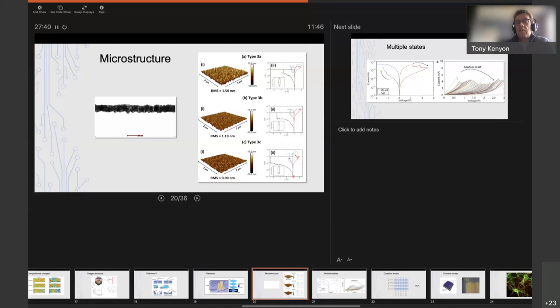What I didn't tell you at the beginning was that we start off with an oxide that is very resistive. And then we apply a relatively high voltage and we form the filament. And then the cycles that I showed you previously are what happens after you form that filament. So we've gone from a pristine state, which is very highly resistive, to a low resistance state. And then when we switch to a high resistance state, we don't go all the way back to the original very high resistance, but we go to an intermediate resistance. So a pristine state, a low resistance, and a high resistance. And that electroforming process is really important because that defines what the filament looks like.